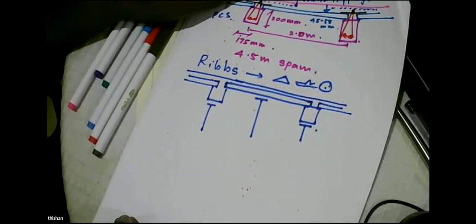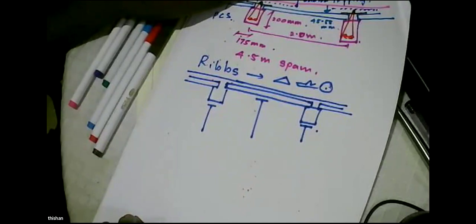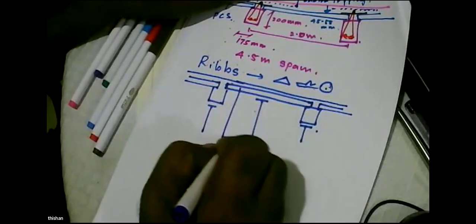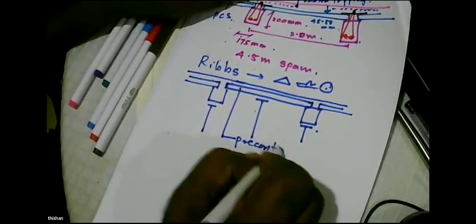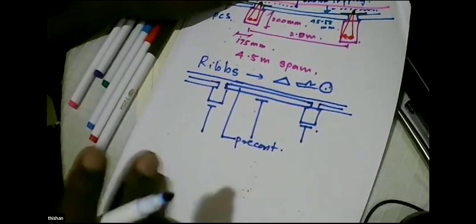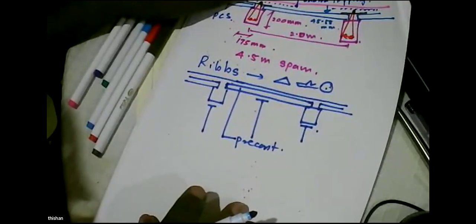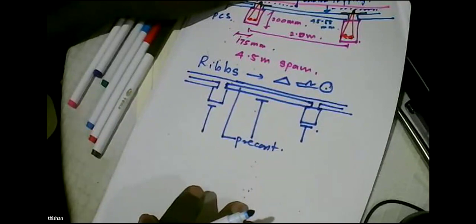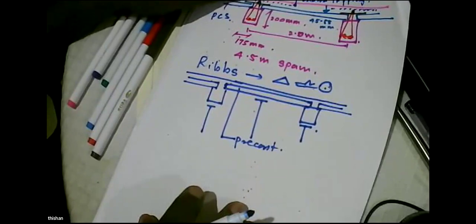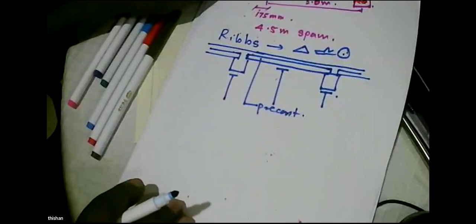These days, the strength development curves are very rapid. So if we keep this moist and cured with ponding for 1 week, concrete will gain a huge strength. So after 1 week, we can remove, and we can precast all these members. We don't have to worry while the columns and all the other things are cast and foundations are done, at a casting yard created on the side of the same site if the space allows. Then we can start casting this. And this is the main innovation that we did.